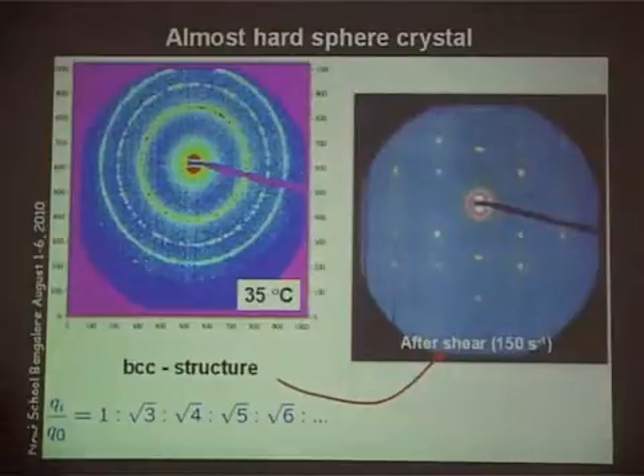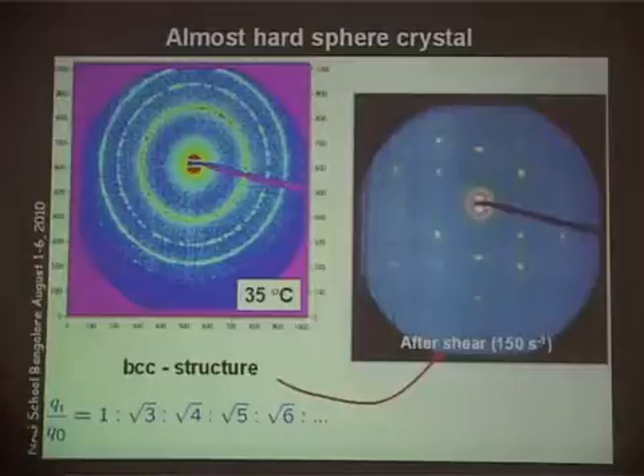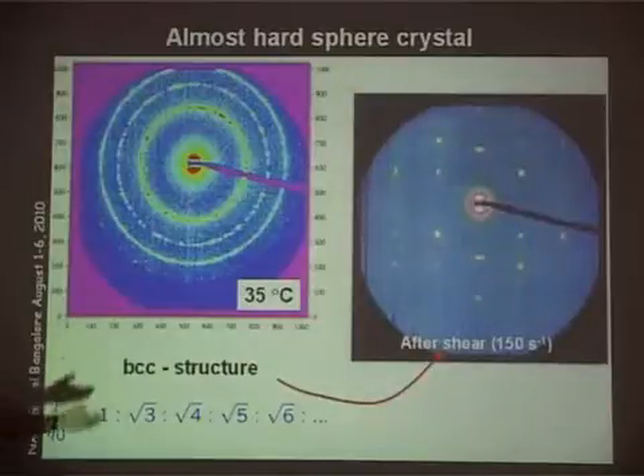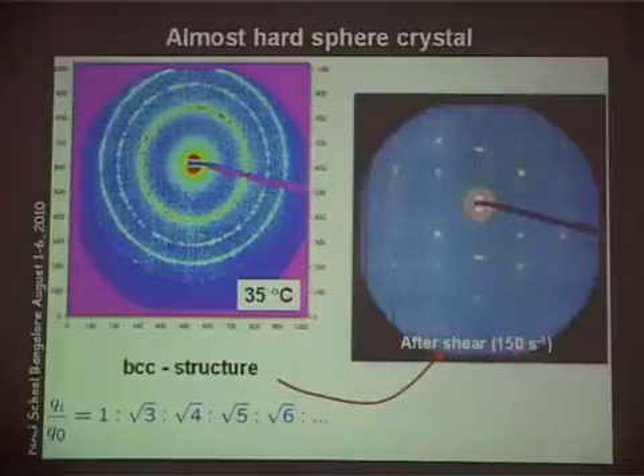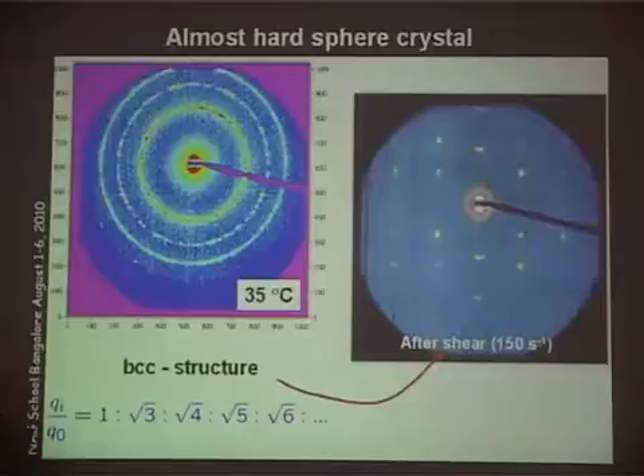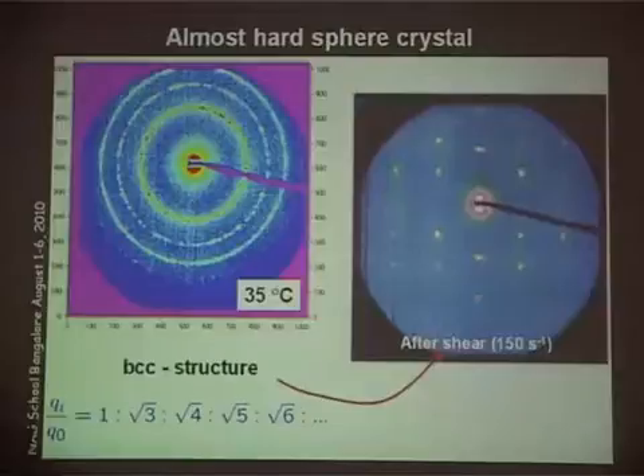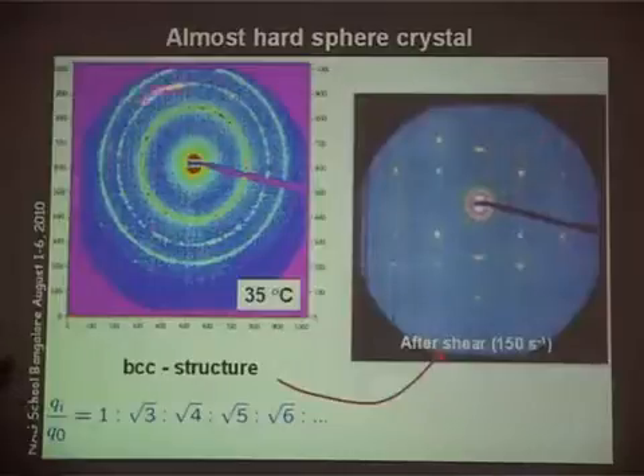If I increase the shear rate further, does it melt them? Yeah. So what you can do is shear harder. This is fairly hard shear. If I go to 300 second^-1, all of a sudden the whole thing gets into what I showed you as a micellar liquid, the diffuse ring. As long as I shear, because I can monitor the X-rays while shearing, it stays like that. The moment I stop, it's instantly a powder crystal again. But I have lost this single crystal. It goes back to this situation.